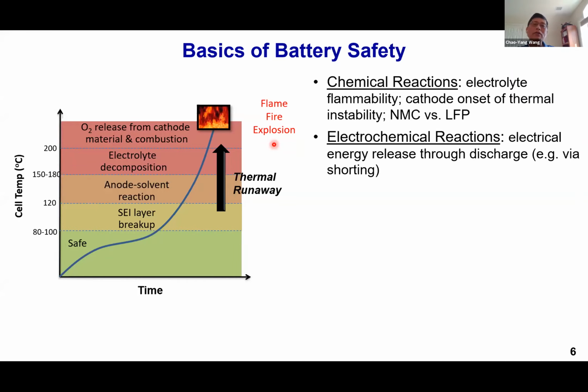But in addition to chemical reactions of battery materials, we also should realize that the battery is actually a device that is capable of discharging energy. So once you have internal shorting or external shorting, the battery will be able to release all the energy contained in it. And that consequence of electrochemical reaction, in the presence of shorting, can be best quantified by this so-called adiabatic temperature. So adiabatic temperature is basically assuming all the energy released by a battery will be absorbed by the thermal mass of the battery material.